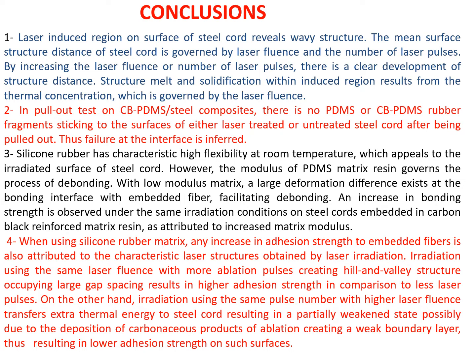When we did the pull-out test, we did not see any matrix fragments on the cord that was pulled out, indicating that the failures were interfacial. The characteristic high flexibility of silicone rubber obviously adds to its wetting of these surface features that we create. However, with low modulus neat resin, a large deformation difference exists at the bonding interface with the embedded fiber, facilitating debonding. An increase in bonding strength is observed under the same irradiation condition on steel cords embedded in carbon black reinforced matrix resin, attributed to increased matrix modulus. So when we use the silicone rubber, any increase in adhesion strength to the embedded fiber is also attributed to the characteristic laser structures obtained by laser irradiation.